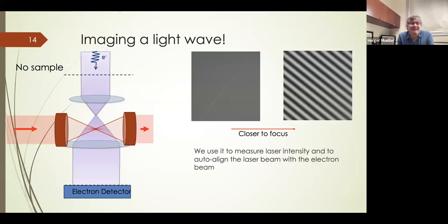Okay. When we first turned this on, our laser beam was not perfectly aligned with the electron focus. And what you then get is a so-called Ronchigram that you can see here on the right. This is one-to-one the data as it came from the camera, unprocessed and all. And the streak, you can see, is actually an image of the light wave. If we bring the beam closer to focus, this feature gets magnified and looks like the one on the right.